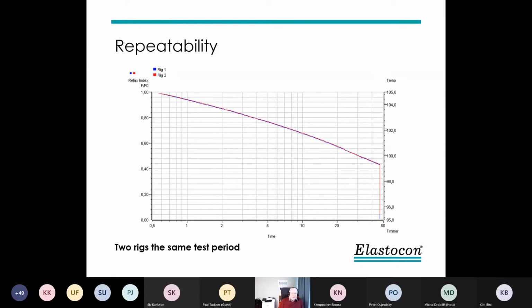Another repeatability test, 2 rigs at the same test period. It may happen that they don't show so accurate, but often they are quite similar. What can cause a difference between the curves can be the lubrication of the samples. If that is not done properly and you get some friction, you may get a little difference in the curves.